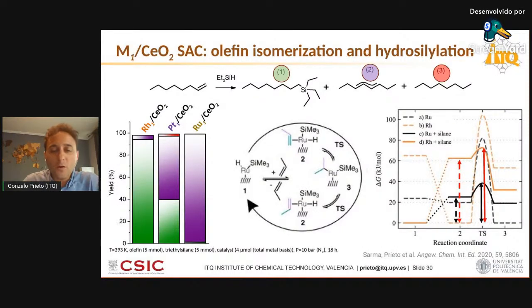And then we went to test their performance for this reaction. And we started off with 1-octene. This is the reaction I'm showing on the top of the slide. 1-octene hydrosilylation with triethylsilane. There are three major products that can be produced under these reaction conditions. First is the desired one, organosilane. We can have there the desired terminal, that's the most valuable product, the desired terminal silane, where the silicon is substituting the hydrocarbon chain at the end. That's the anti-Markovnikov regioselective product. But we can also have the Markovnikov one, where there is a methyl substituent, and then there is a branched chain for our organosilane. But those are the desired products, organosilanes.